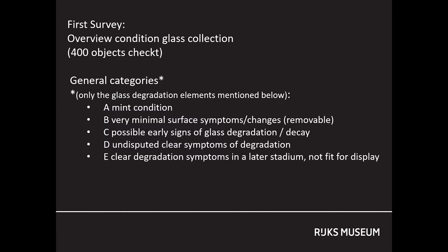We started the survey with the core collection, which maintained around 400 objects of vessel glass. It was supposed to be a general condition survey to create a condition baseline. So the condition in its totality was checked. So aside from degradation symptoms, also chips, breaks, and restorations, etc., were put in the survey. The glasses, we categorized in 5 categories according to their condition and stability, where A was mint condition and E was general bad condition.